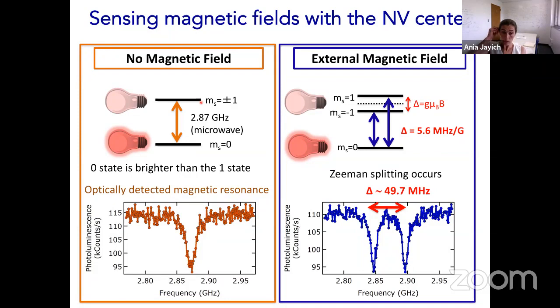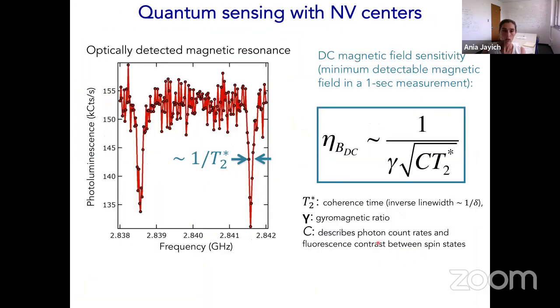Also want to stress that the quantum coherence of the NV center is very important in determining its sensitivity. So in fact, the line width of these transitions tells you how well you can resolve small shifts in the magnetic field. Here I've taken a zoom in of one of these peaks. In fact, you see a big splitting here, which is the hyperfine splitting between the electronic spin and the local nuclear spin. That local nuclear spin also produces a magnetic field that the NV center is sensitive to.